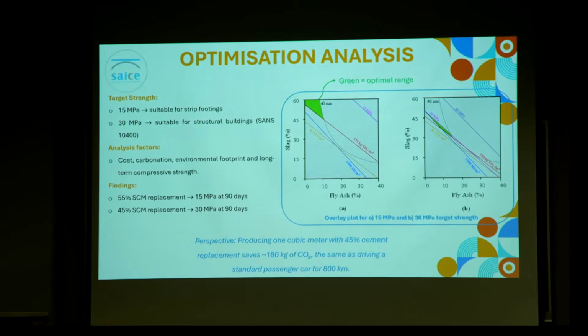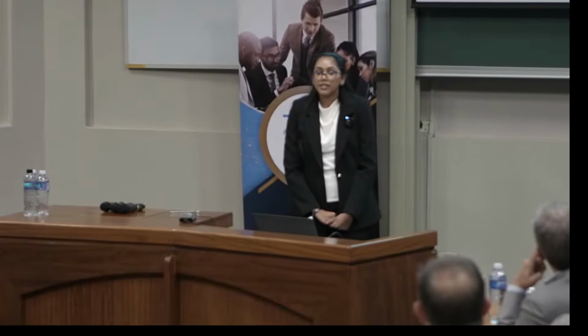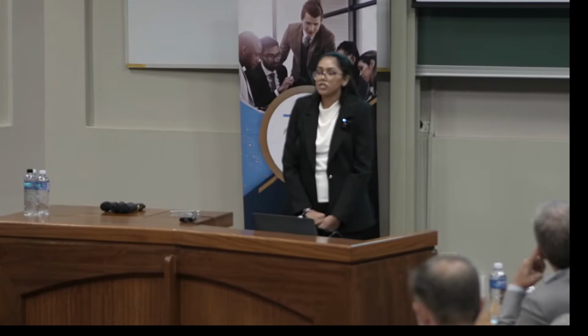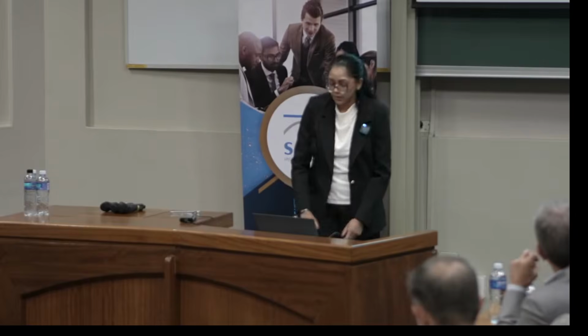To put this in perspective, producing 1 cubic meter with a 45% cement replacement can reduce emissions by 180 kilograms of CO2. This is equivalent to driving a standard passenger car for about 800 kilometers.